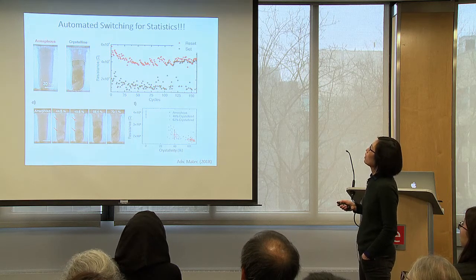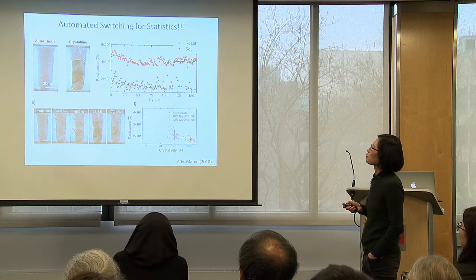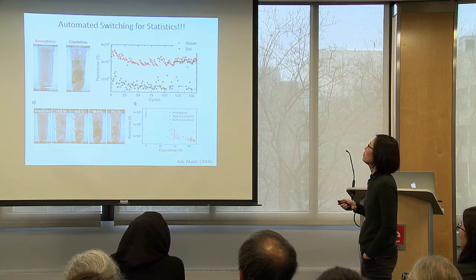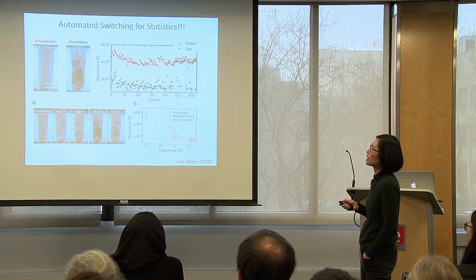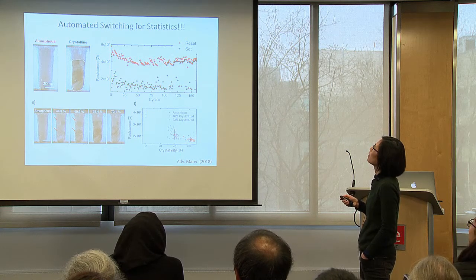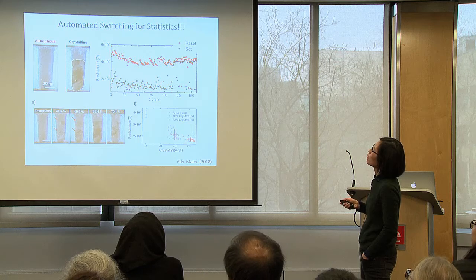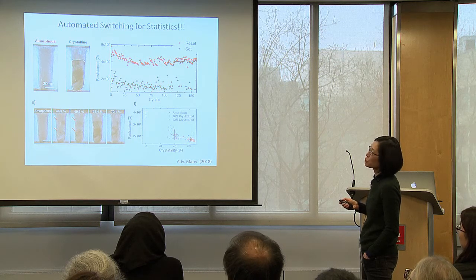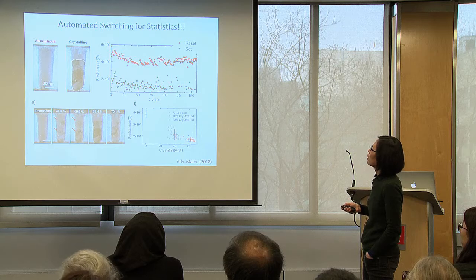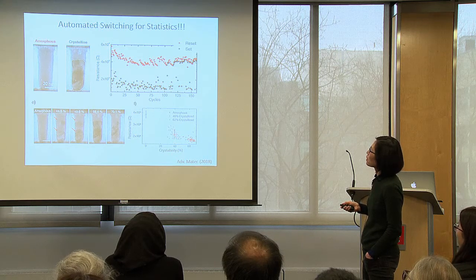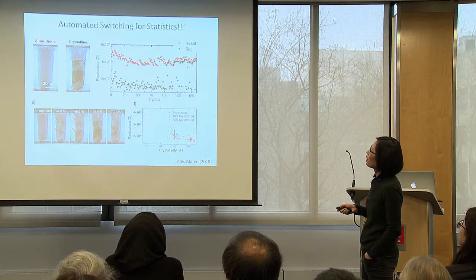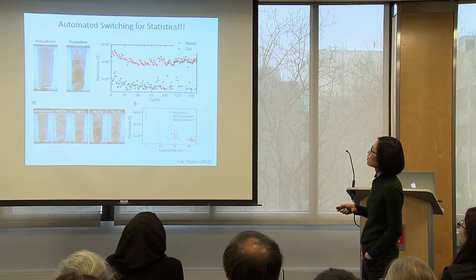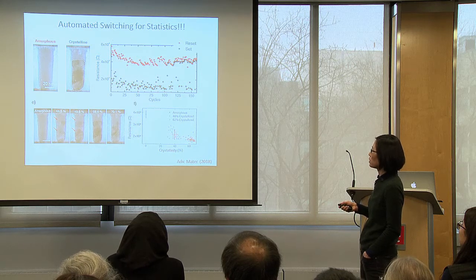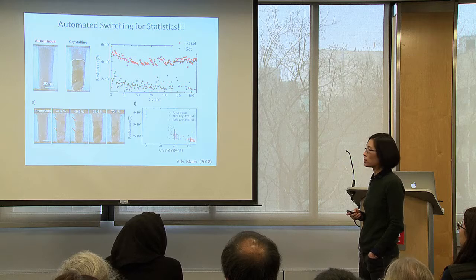Here, with this device, we were able to cycle about 170 cycles up and down. These values are not the same as the wafer values, but here is now our on and off. And we can now do statistics because we have a lot of cycles. So we can say a lot of times it's about 40% crystallization, that's the bottom little part here, and the other times, somewhere in the center, is another crystallization fraction. So we have these clusters of crystallizations.